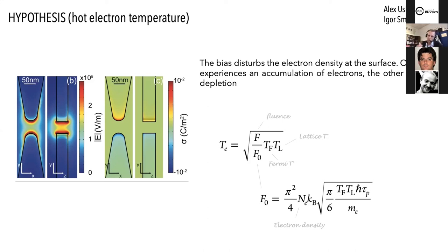And so we looked at the problem also from this electron picture, the hot electron picture. And of course, when you apply a bias in the gap, as pictured here, you have a static electric field, which is basically localized at the tips. And you have this so-called lightning rod effect, where you confine the electric field at the apex. Of course, this electric field is associated with a change in the surface charge density. So you may have an excess of charge here, and a depletion of electrons on the other side. So we have basically a capacitive effect in the system.